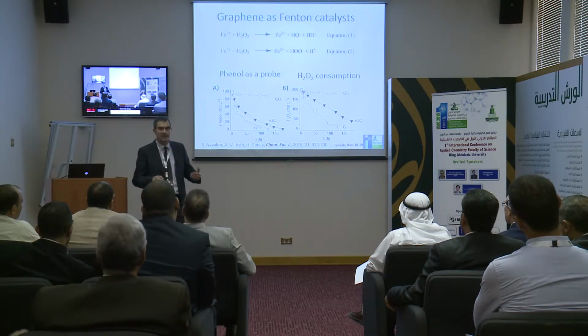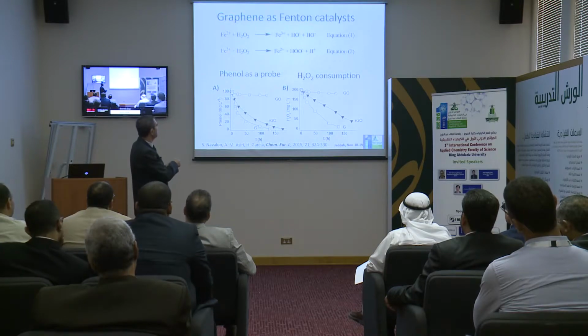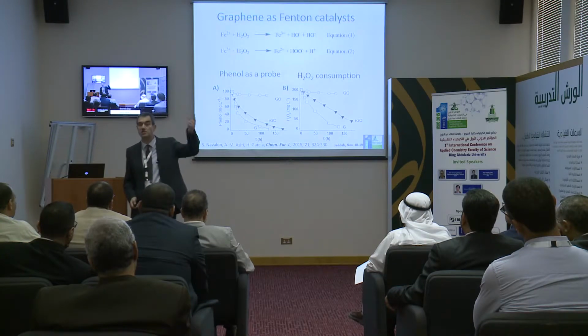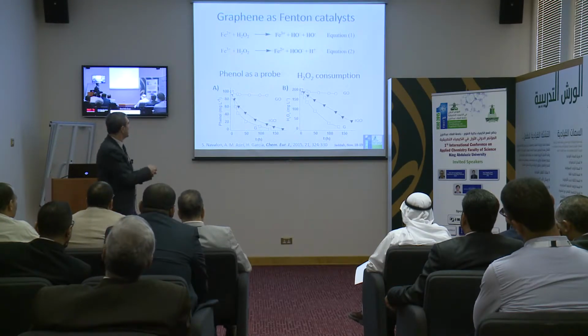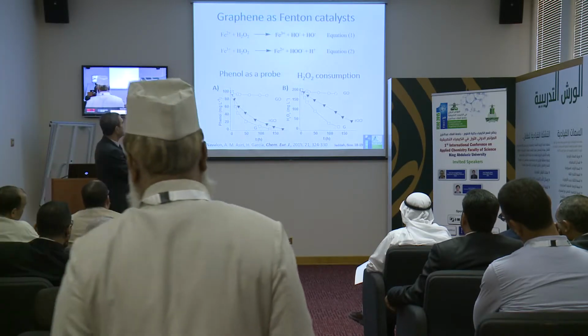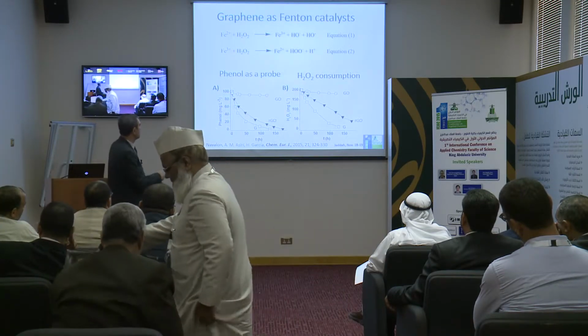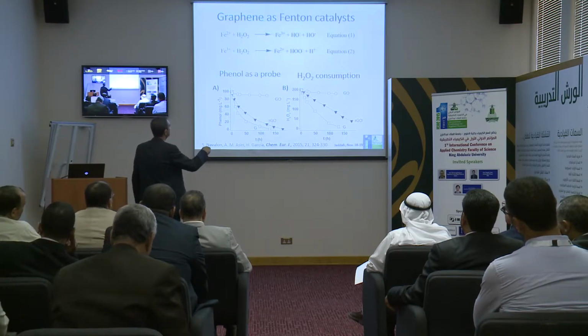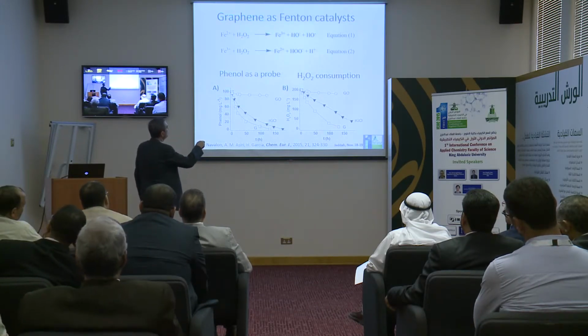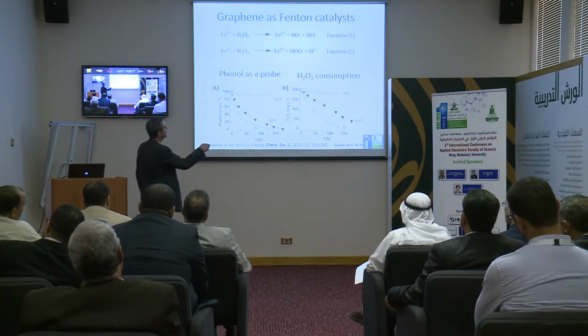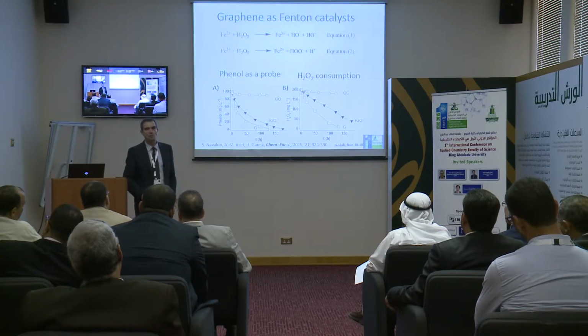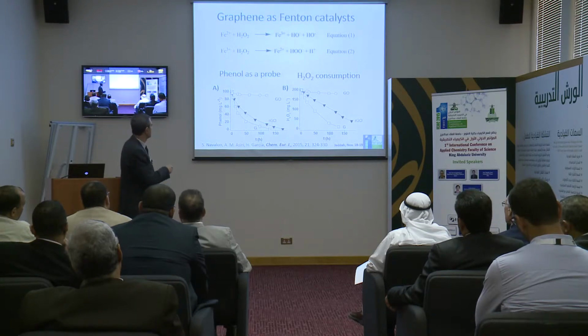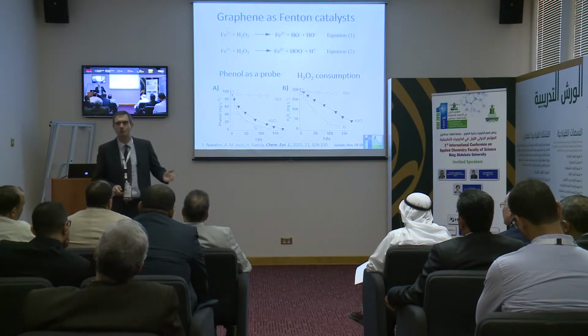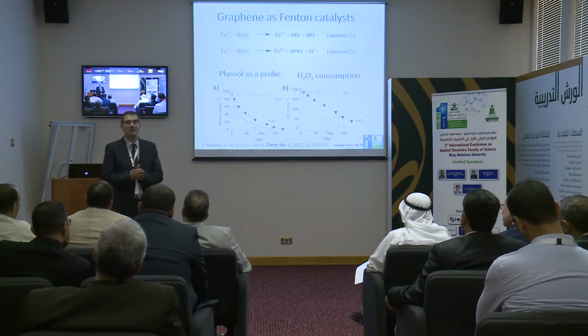The other thing is that then iron 3 becomes reduced to iron 2 also by hydrogen peroxide. So hydrogen peroxide is very nice because it can oxidize and can reduce. Here what we are doing is oxidation, but also here you are using the reduction. So the combination of these two processes, at the end, is that with two molecules of hydrogen peroxide, one molecule gives hydroxyl radical and the other molecule is decomposed to oxygen and performs the reduction of iron 3 to iron 2. If you go to the literature, all the examples have been reported with metals. So we are talking about metal-free catalysis.